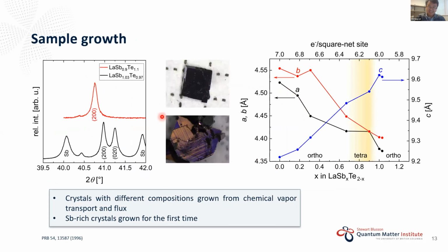So from here you can see there's definitely twinning. This image here is taken with polarized light, and you can clearly see the twinning. So we did not detwin the crystals. I had a look at these crystals, and I chose the ones where I saw big enough domains, or big enough twins, that we could probe them with the spot size that we have at CLS. So we're talking about on the order of 20 by 150 micron. And just by scanning the sample, we were admittedly lucky enough to find a region where we probe a single twin. Oh, I see.